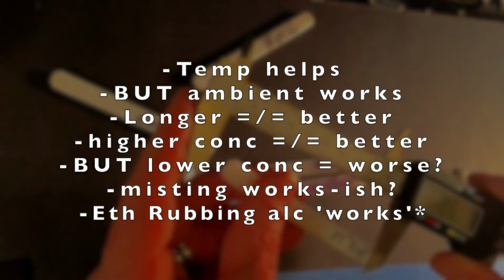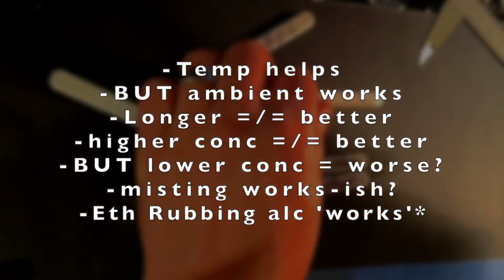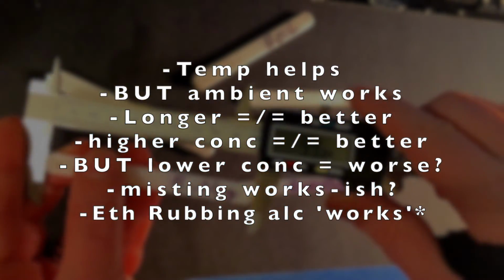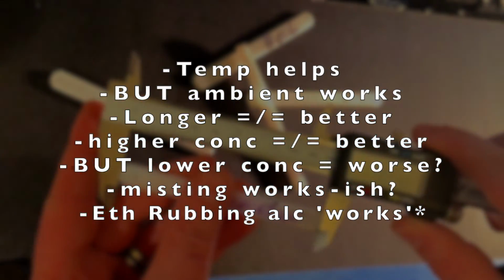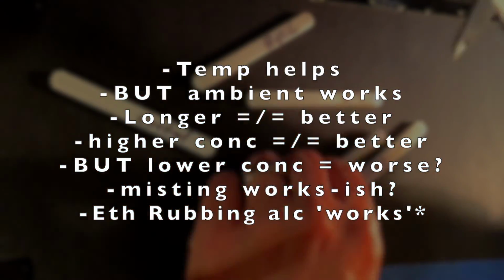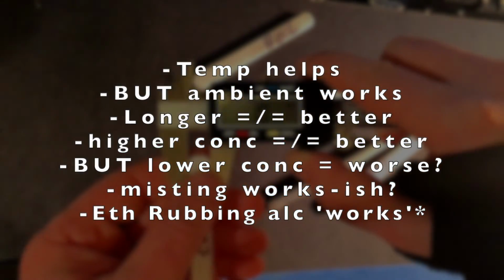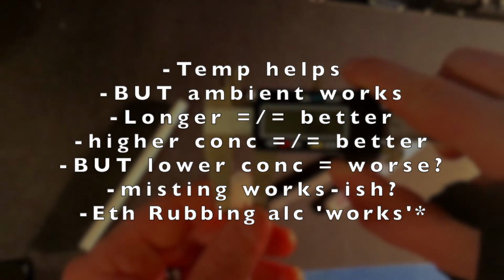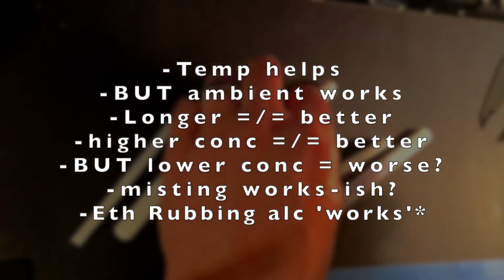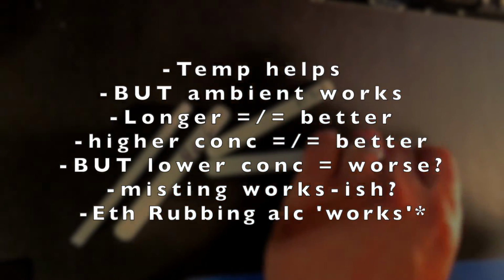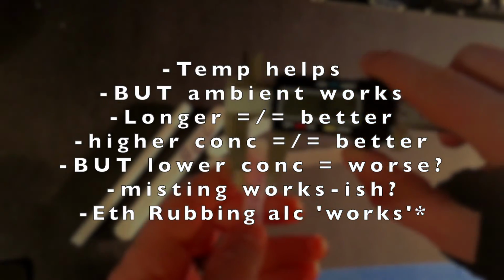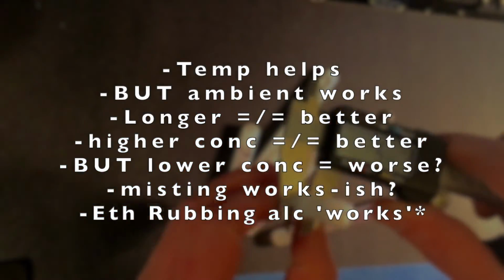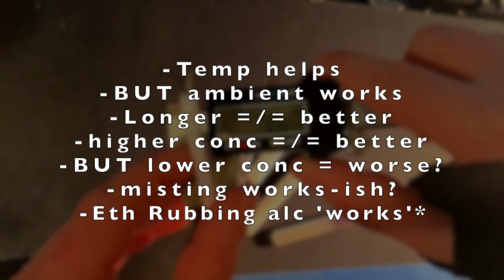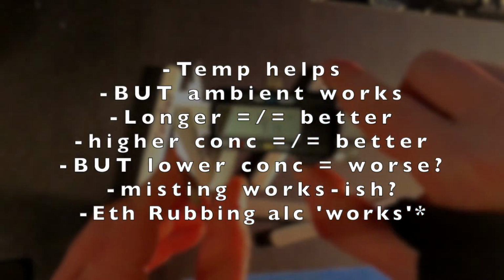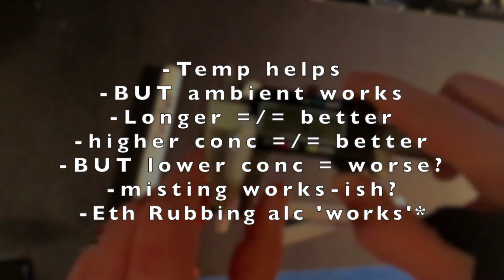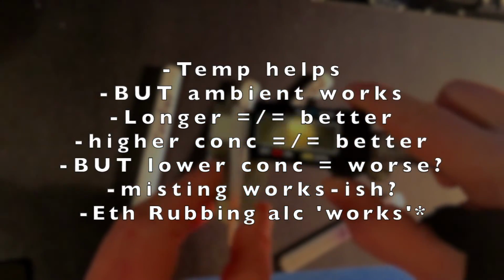In terms of concentration of alcohol to water, it doesn't necessarily seem that a higher concentration is better. In fact, we saw in that test where we did 75 versus 50 that 50 was better than 75, which means something around 50% alcohol, 50% water, i.e. 100 proof or 120 proof, is probably the sweet zone, but that may or may not change depending on temperature and length of time you leave it in there and things like that. We also saw that the misting works-ish, although a lot of experimentation has to be done there, and the ethyl rubbing alcohol off a shelf, if you just want to try this, works in quotes, but because of the mystery meat, I don't know what's in your rubbing alcohol, so it may be a disaster.